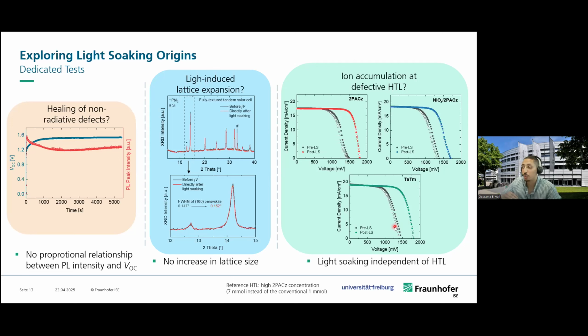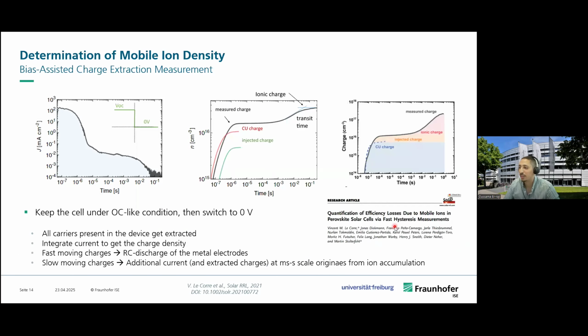So then we turned our attention to mobile ions. And in order to estimate the mobile ion density in our device, we use the technique that I think will make Vincent very happy. It's the bias-assisted charge extraction measurement, where we can get an estimation of the mobile ion density by making 3 steps. First, we have our cell in an open circuit-like condition, where then we switch to 0 volt. And when we do this, all the carriers present in the device get extracted. And depending on the extraction time of the different charges, we can attribute them either to a capacitive charge, injected charge, or ionic charge. And in this region of slow, let's say, a millisecond regime, we can get an estimation for the mobile ion density that we have in our device.